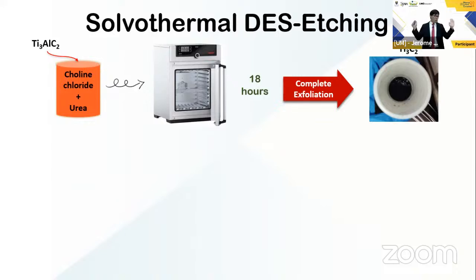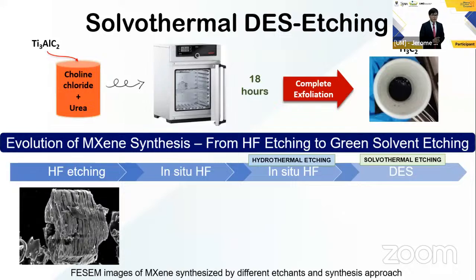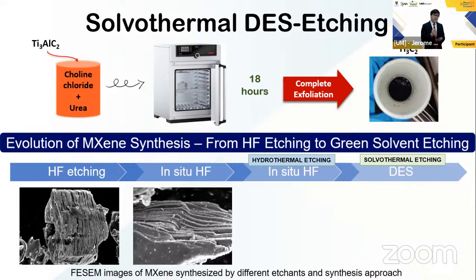So let us now revise the timeline of MXene synthesis, of how it has evolved from when it was first discovered. In 2011, pure hydrofluoric acid, very nasty, was first used to make MXene, and it produces this beautifully etched MXene. Three years later, in situ HF was used, and we can all tell the effect of exfoliation is less than stellar. The layers are not as open, they are not as wide, and it also suffers poorer electrical conductivity.